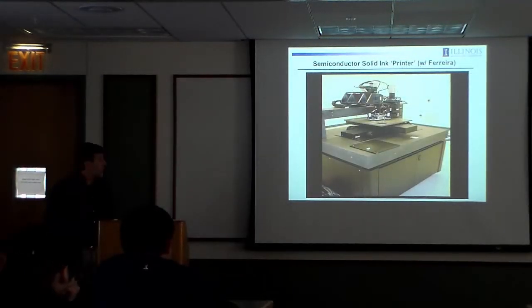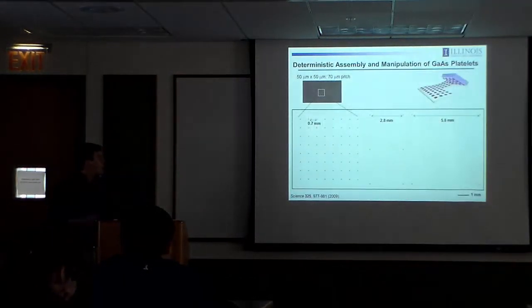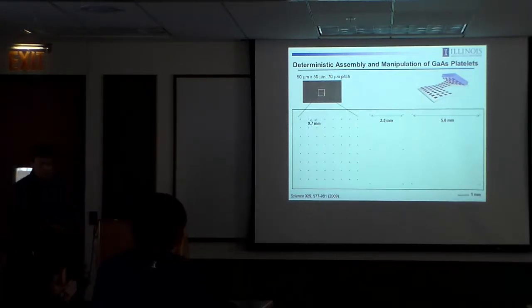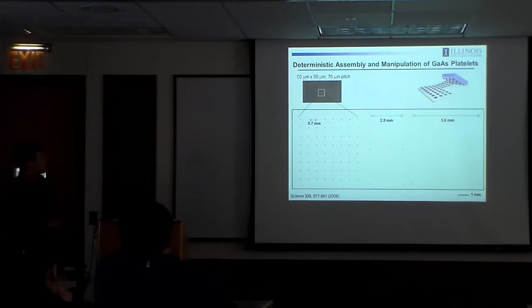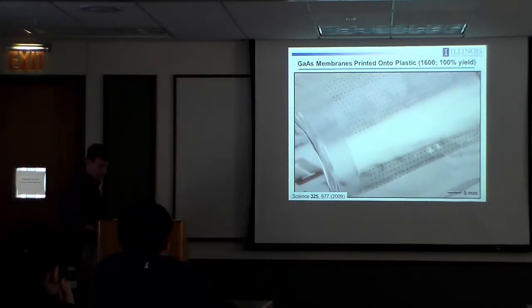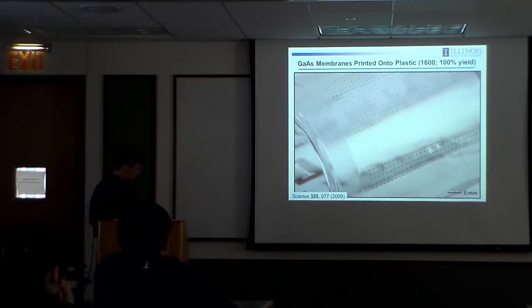You can build tools like that to do it in an automated way. You can take arrays of these very tiny things in dense configuration and spread them out any way you want just by programming up the printer in an appropriate way. So here you're going from 50 by 50 micron nanomembranes on a 70 micron pitch, and then you can spread them out, 0.7 millimeters, 2.8, and a little over 5 millimeters just by programming the stamp. And that turns out to be powerful, and I'll show you how that works in the context of optogenetics in a few minutes. So here's an example.